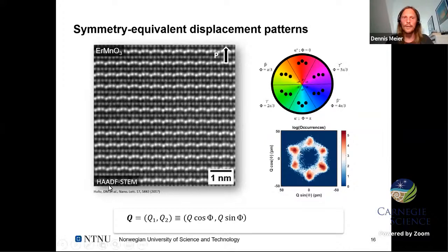Here you see what's happening with the rare earth atoms. On the left-hand side, you see an STEM image. The brighter atoms are erbium in this case, and they show this up, down displacement in between the manganese, which are separating the erbium lines. And the structure can be explained or described in terms of a sinusoidal wave. So the structural order parameter here has an amplitude and a phase. And because of the symmetry of the system, you cannot just have one specific phase.